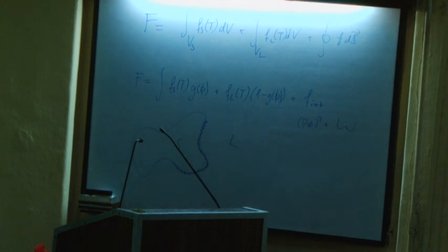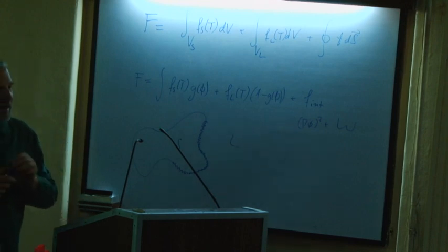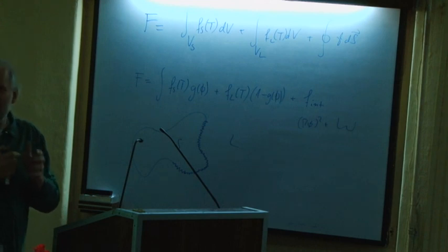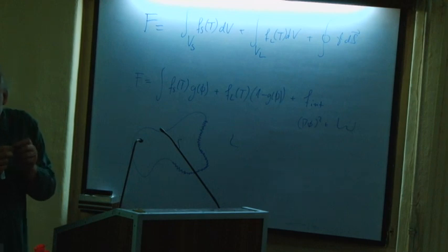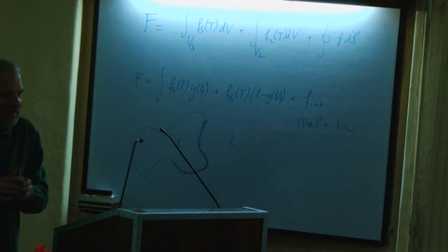Okay? So now I need equations of motion. So first of all, the phase field. I told you it's an order parameter, the difference between ordered and disordered structure. So is it conserved or non-conserved? It's non-conserved because in order to go from a disordered liquid to an ordered solid, atoms have only to move about a fraction of the atomic spacing. They just have to jump in the right place. So this can take place in a finite volume of liquid without transport of atoms.